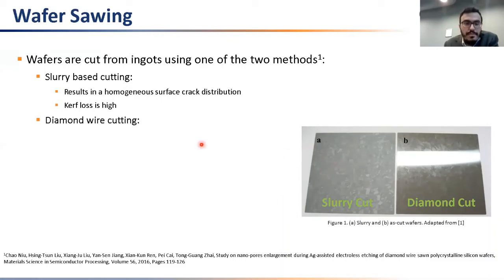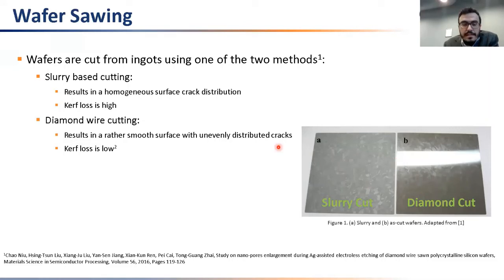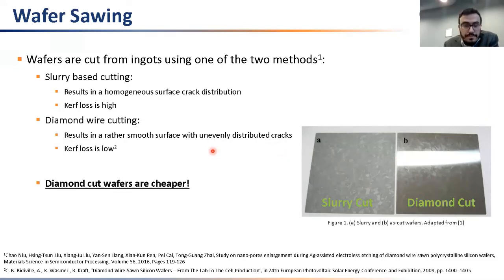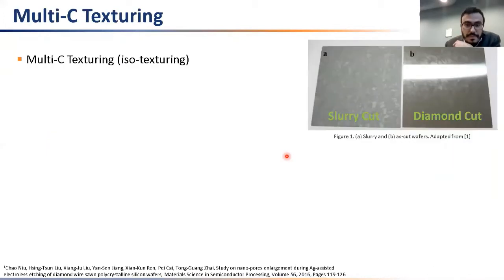However, when you use diamond wire cutting, it results in a rather smooth and very shiny surface, and it has a low kerf loss. This means that when you use diamond wire cutting of your wafers to produce solar cells, you are using cheaper materials because of the less material loss from the kerf loss.